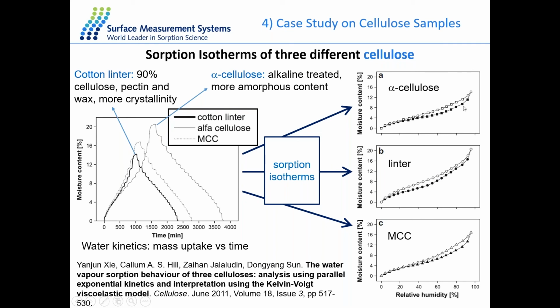And you may also notice that the hysteresis gaps for different cellulose samples are located in different humidity ranges as well. And this is due to the structure inside the sample, like the collapse of the nanopores or the swelling of the internal structure. And also there is a possibility of a contribution from capillary condensation as well. And these are just very straightforward experiments we can perform with the DVS technique for the characterization of the solid cellulose material.